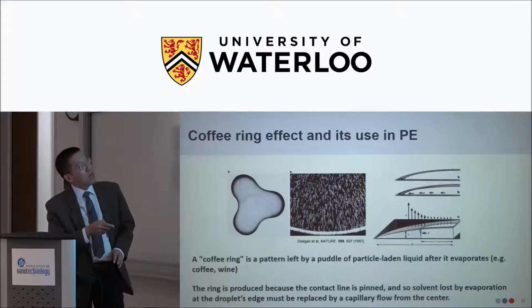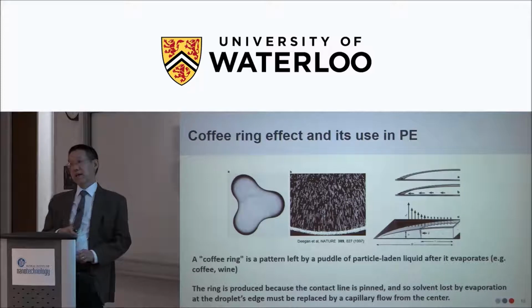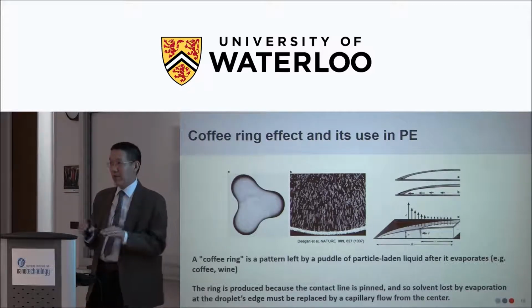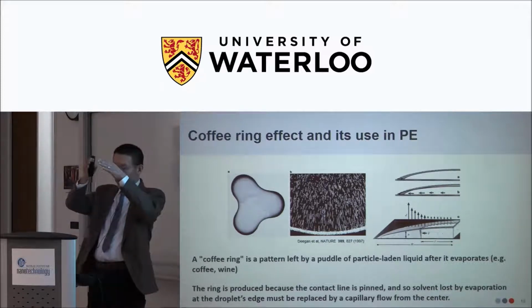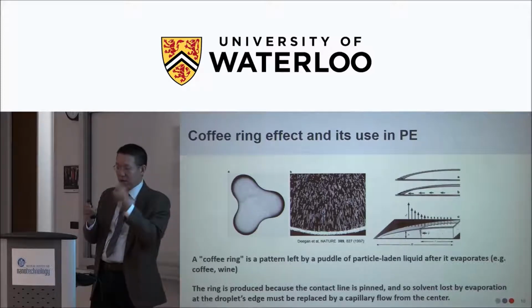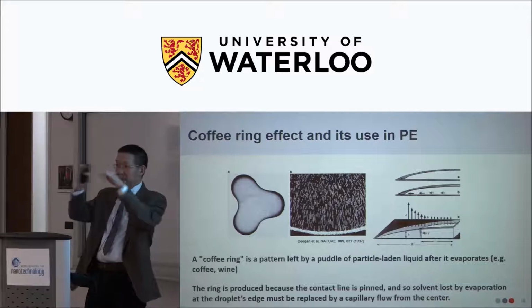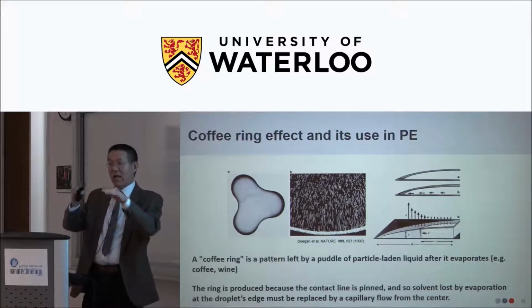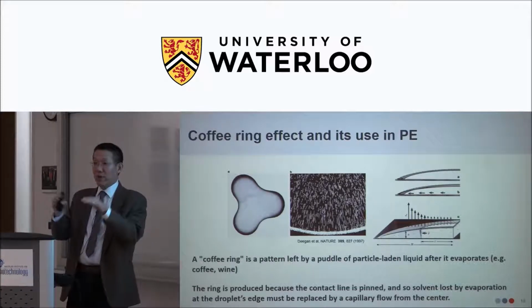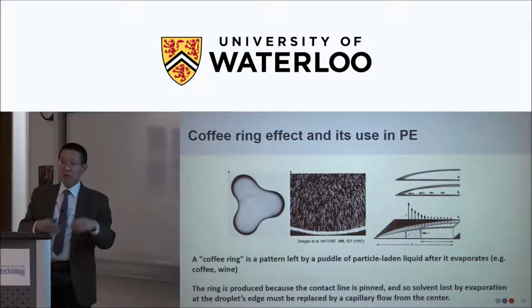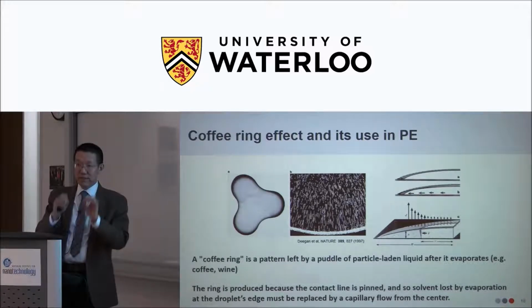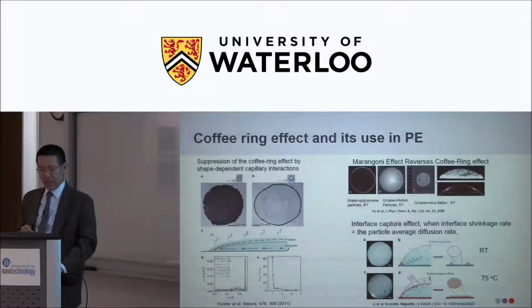When it dries up, we want to use this area as our pinhole-free area. Because when you dry the film, some particles may cause pinholes or some structure. But you have a lateral flow of dielectric material, and our flow will refill any pinholes you have, right? So the result is that you get a very nice, dense, pinhole-free dielectric layer.